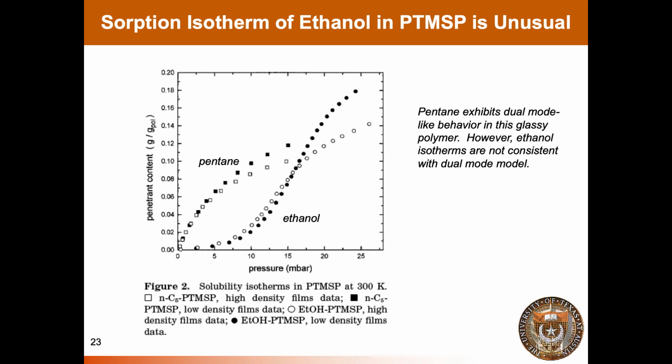It turns out that it is a glassy material with a very low density, that is a high free volume. It's not stable. Its properties change a lot with time. It undergoes what we call physical aging, where gradually the polymer simply consolidates and properties change with time. It's also been looked at for ethanol water separation. And so these are the two applications that were underpinning this particular choice of penetrants in this study.